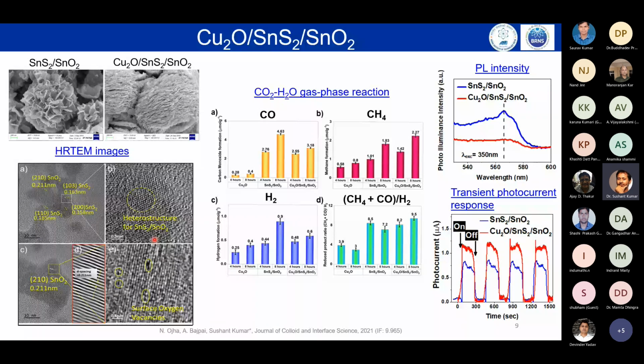Now, these were our characterization results, and we performed the CO2-H2O gas-phase reaction. We again saw CO, methane, and hydrogen formation. And let me tell you that CO and hydrogen can be seen as syngas, which can be transformed into methanol. When we checked it, we saw that the Cu2O, SnS2, and SnO2 was giving more methane and less CO, and SnS2 and SnO2 alone was giving more carbon monoxide. So to understand this, we looked into the mechanism.